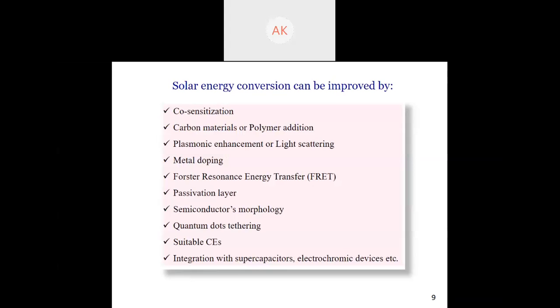First is co-sensitization. Suppose I'm using CdS, the visible light harvesting quantum dots, and I co-sensitize my film with PbS. Now, lead sulfide is a NIR light harvesting quantum dot. So together, we can have a broader utilization of the solar spectrum. You have visible light, you have NIR light, so there is broad spectral utilization. Secondly, we can have carbon materials or polymer addition. These materials do not absorb light themselves, but their energy alignment is suitable and they're also highly conducting, so they escalate the charge propagation throughout the cell.